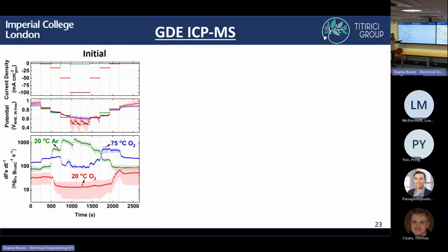So as we get to around 15 milliamp per centimeter squared, we see actually a decrease in the iron concentration that's measured by ICP-MS. Whereas if we look at oxygen at 75 degrees, as we step down in potential with the same current density, we actually see initially an increase in the iron concentration and then a decrease in the iron concentration as we go to higher current densities. So this is kind of confusing, but I'll explain in the next slide what we think is happening.